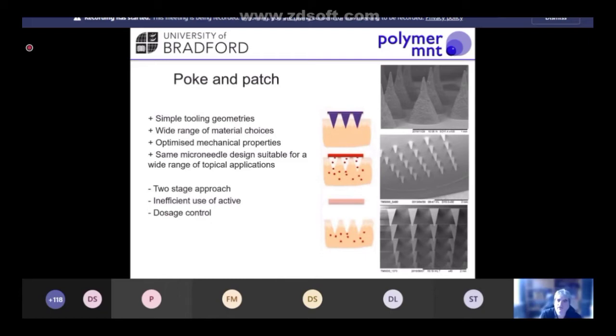And the advantage of doing this is that we have very simple tooling geometries that we create for our manufacturing processes. So these are going to be lower cost than some of the more complex ones we've seen for the hollow systems. It also gives us the opportunity to explore a wide range of material choices. The material used here doesn't really affect any of the drug delivery aspects of the process. It's all purely geometry defined. So what we can do is we can really optimize the materials we use here to get the best possible mechanical properties to ensure we get really good penetration behavior and we don't get any breakage of needles as well.